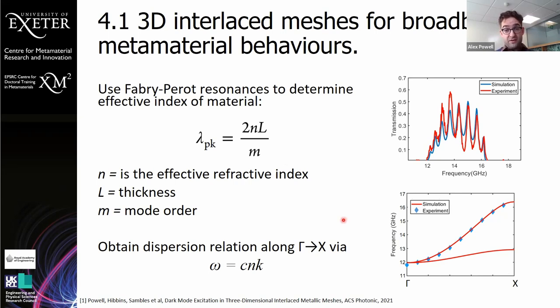And we can use that to get the dispersion relation for the transverse mode along the axis that we're looking along through it. So we looked along one of the rods, along one of the principal axes of this material. And we're able to experimentally determine the dispersion relation to the resolution that we have from these Fabry-Perot resonances. So that was quite nice.